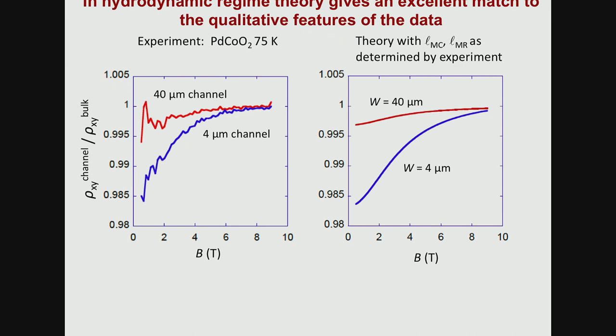if you're going to get into electron hydrodynamic calculations, you have to be very careful. If you use a Navier-Stokes-based approach, you can still put some momentum-relaxing scattering in as a phenomenological parameter. So you're very well capable of studying the crossover from hydrodynamic to ohmic behavior. However, that whole framework is not capable of including this ballistic regime that I had to admit to when you asked me. And so what we thought was, we really need to check whether this is clearly a signal consistent with hydrodynamics, but is it a unique signature of hydrodynamics, or could it also be explained by other effects?